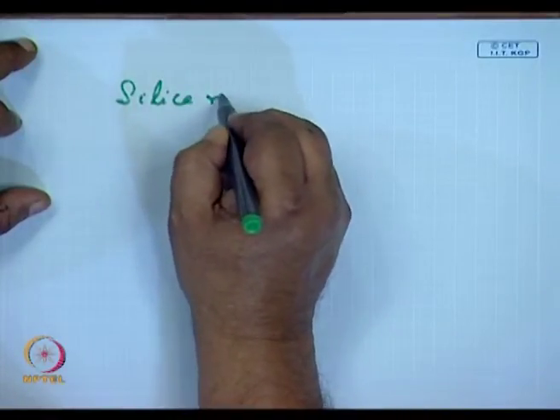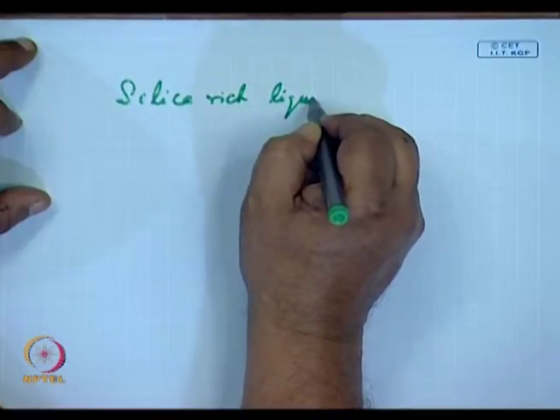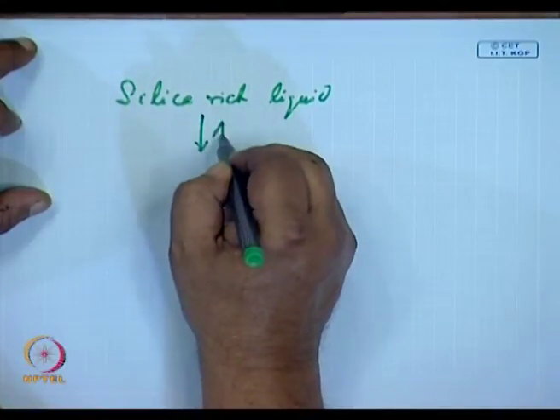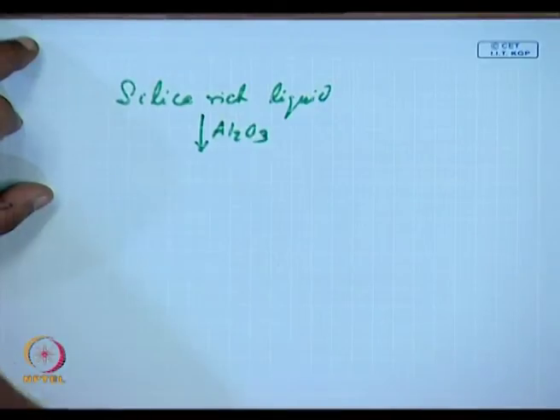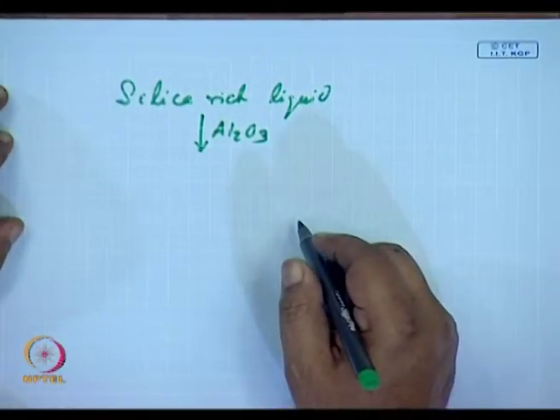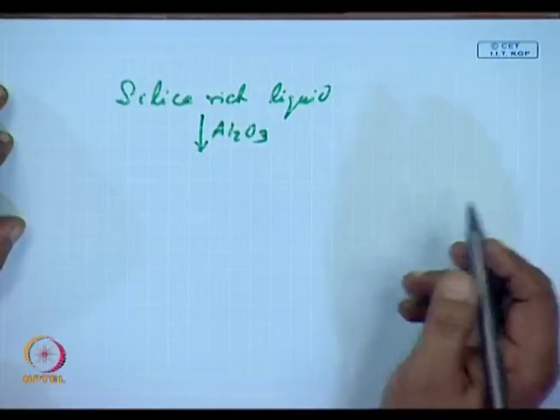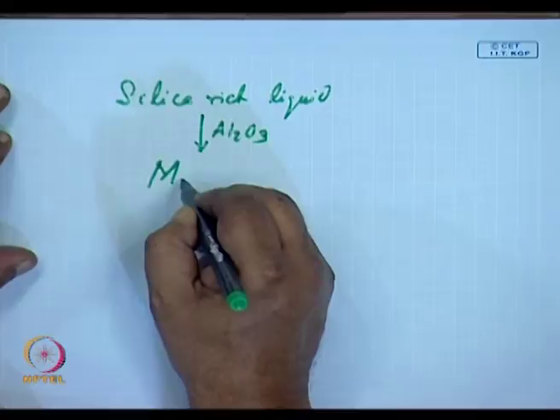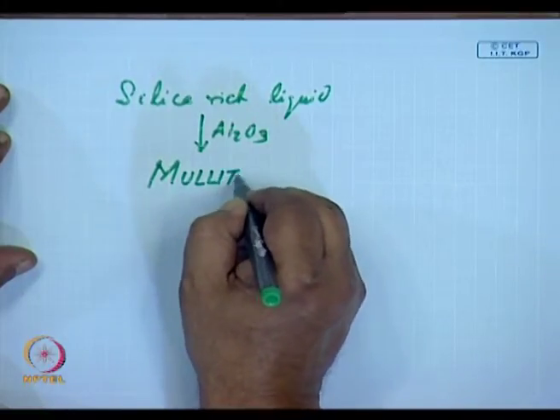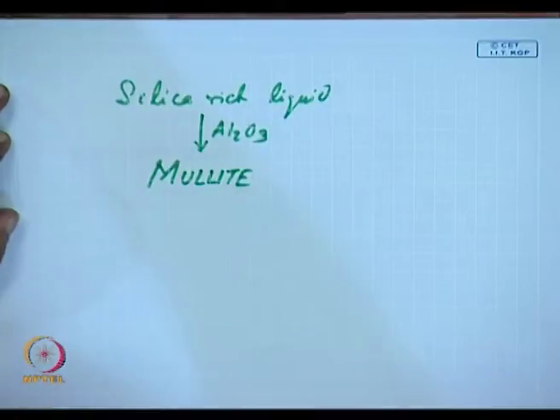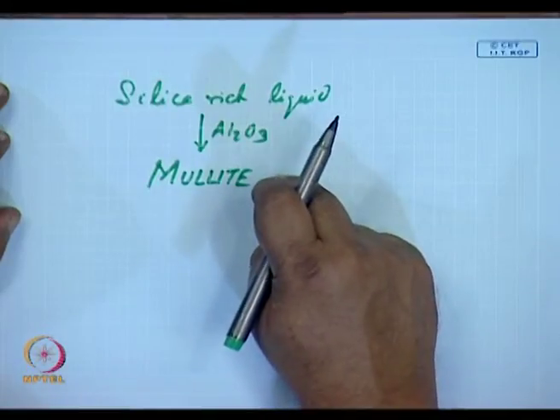The silica rich liquid, as a very simple case, would react with alumina. Now a new product would be generated, which is mullite, a mixture of alumina and silica. It is a compound, specific compound with a specific melting point. I am not taking up the composition because I shall do it when I discuss two-phase diagrams.